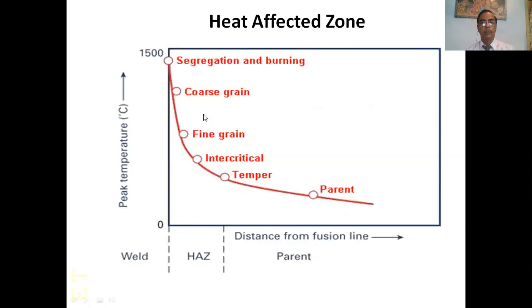Heat affected zone. Segregation and burning at 1500 degrees centigrade. Coarse grain, less than that, then around say 800, fine grain, intercritical, less than that, then tempered, then parent. This portion is called the HAZ, plotted against distance from the fusion line. This is a parameter. This is the weld, and peak temperature in degrees centigrade, 1500.